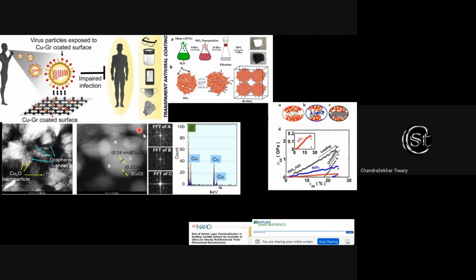So for applications or utilities around you where you need high transmission, you can utilize graphene as a template and then decorate this graphene with antimicrobial nanoparticles. For example, copper oxide, which is shown here. You can see clearly they are nicely decorated on the graphene sheet, and this graphene sheet is coated onto those objects, where you can get functional applications also.